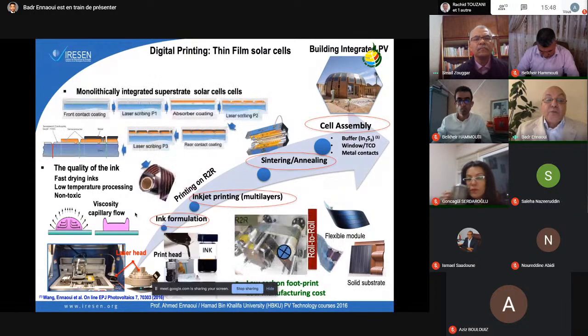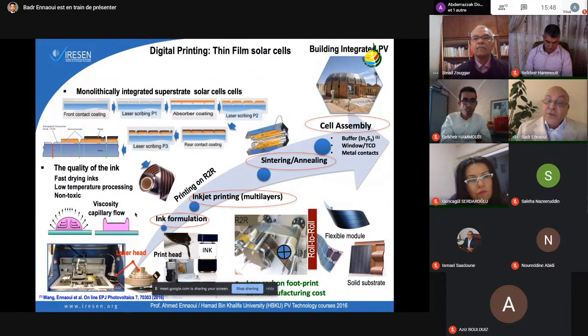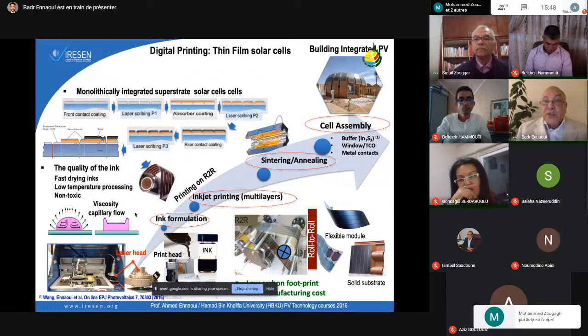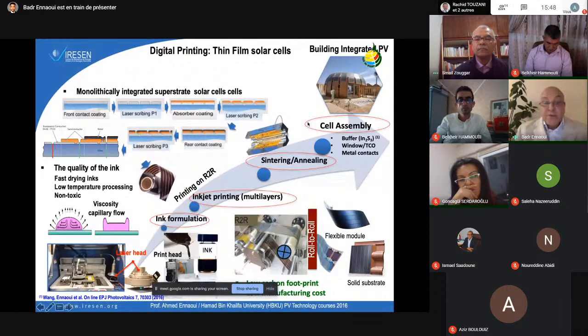So we were able to make a roll-to-roll, but still many problems: the quality of the ink, the fast drying of the ink, to make the low temperature processing, because if you want to have a low cost printer for large scale, you have to work at low temperature, and always use non-toxic precursors. So this roll-to-roll is one of the best methods for the future, which we show is working very well. So you can go from ink formulation from the first step to the end to make even building integrated photovoltaics, which I showed you in the beginning in the photovoltaic portfolio.